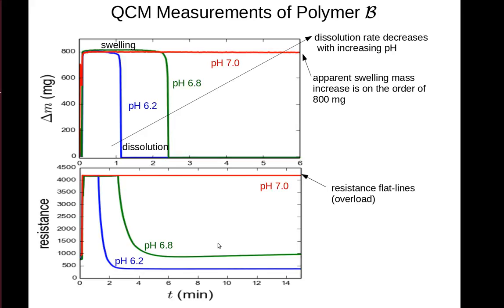It's worthwhile to use these techniques to explore a new polymer that has slightly different characteristics. First, looking at the QCM measurements. Again, mass versus time. We'll call this polymer B. It behaves very similar qualitatively to the first polymer. At a high pH, there's very little dissolution. At the lowest pH, there's rapid dissolution, and at an intermediate pH, there's intermediate dissolution. The pHs are shifted slightly from the first polymer due to its chemical composition, but again, the qualitative trends are the same.